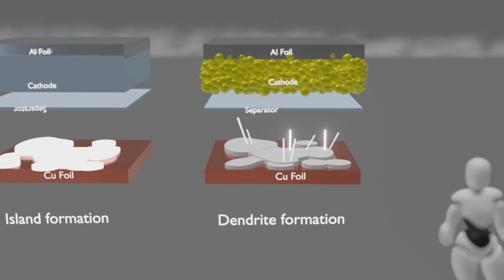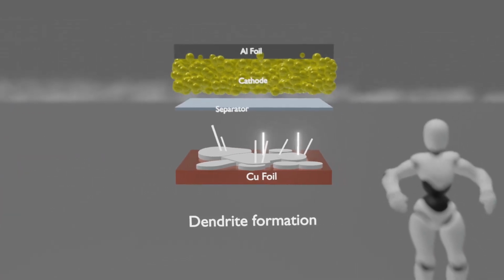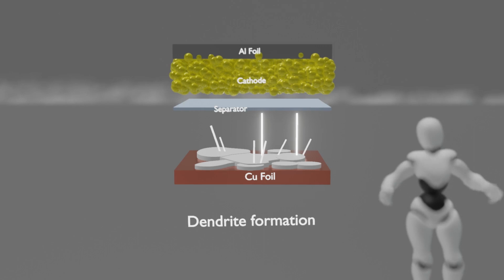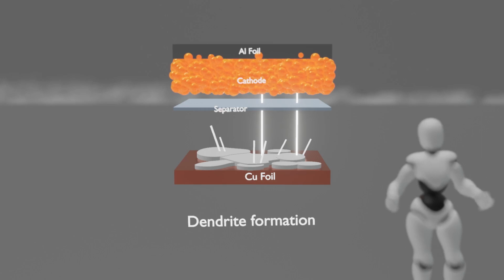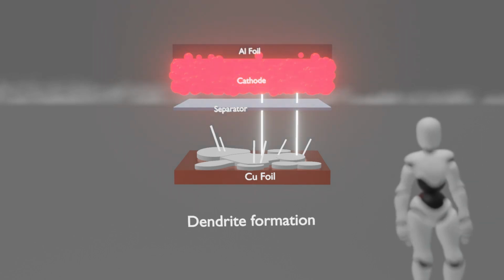When this happens, the consequences are catastrophic. As the lithium metal continues to grow in this form, it eventually breaks through the separator and reaches the cathode. When this happens, the energy stored in the cathode causes an instant discharge through the link between the lithium metal and the cathode material, causing the temperature of the battery to skyrocket.